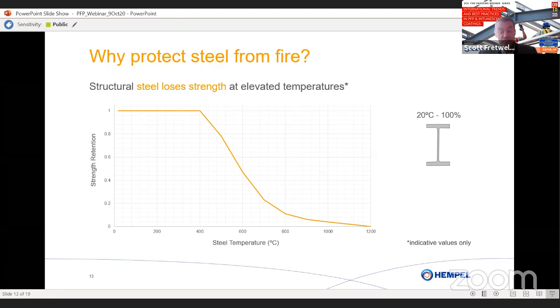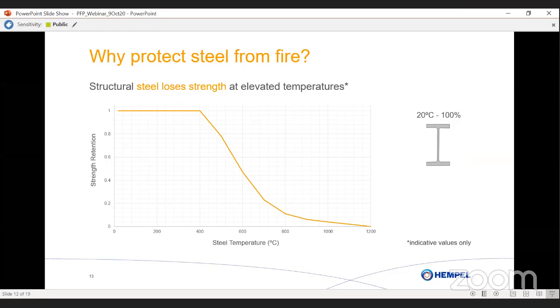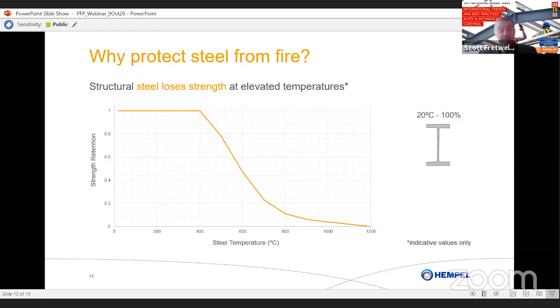You will see on the right of the graph the strength retention. One is a steel retaining 100% of its strength down to 0. And horizontally across the bottom, the steel temperature. So we start off at ambient temperature, a room temperature, around about 20 degrees C. And we can see from the icon on the right, the steel retains 100% of its strength.